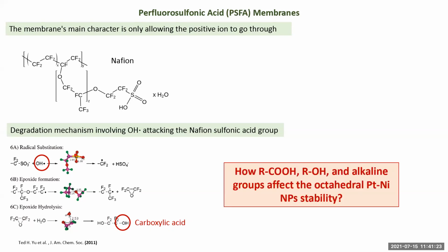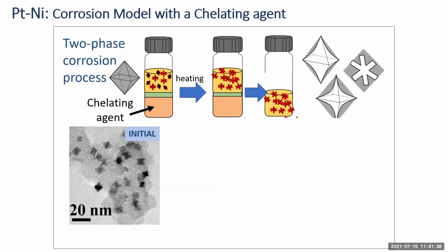So what we want to know specifically is how carboxylic acids or other types of groups, similarly acidic or even not so acidic, will influence the stability of octahedral platinum nickel nanoparticles. So what we have here is a two-phase corrosion process system. We have the particles suspended in the organic phase, and in the aqueous phase, we have a chelating agent. This is an agent that traps the nickel, with a very high affinity to nickel. And these chelating agents contain organic groups, for example, the carboxylic acid.